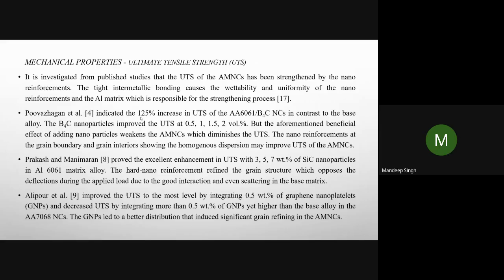So Poovazhagan et al. indicated the 125% increase in ultimate tensile strength of the AA6061 boron carbide nanocomposite in contrast to the alloy. The boron carbide nanoparticle improved the ultimate tensile strength at 0.5, 1, 1.5, and 2 volume percent.